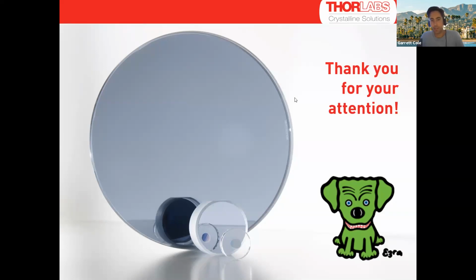Kevin Romero asked, can you have multiple HR regions over say 1 to 12 microns? In principle, yes. It's an interference coating, so I can design AR coating, mid-level coating, HR coating. I can do all the tricks you do with interference coating to get whatever weird shape reflectance spectrum you want. Keep in mind though, as I mentioned, our refractive index contrast is not so large, which means it's tough to make, say, a steep filter. If I wanted HR here and high transmission here with just a vertical line, you really win if you have high index contrast. A good example system is silicon silica, which has a giant refractive index difference. Because ours isn't very severe, it takes a thick stack to tailor a certain reflectance spectrum.